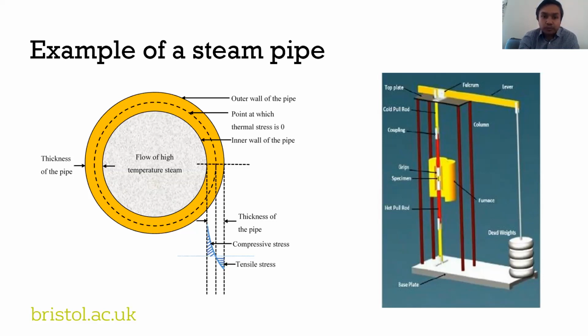But in a real-life scenario, it's much more complicated. For example, when the plant first starts up, when the steam first goes through this pipe, the inside of the pipe gets heated up pretty quickly and it tries to expand, but the outside still remains cold, so it cannot expand. So it puts in a lot of plastic deformation, for example compressive stress. During shutdown, it's vice versa. And maybe there is a weld in the pipe which has some additional stress we call residual stress. And then there is microstructural variation, and creep is very sensitive to this microstructural variation. So this all makes it much more difficult to predict simply with empirical relations or a simple test like the one shown in the right-hand figure.